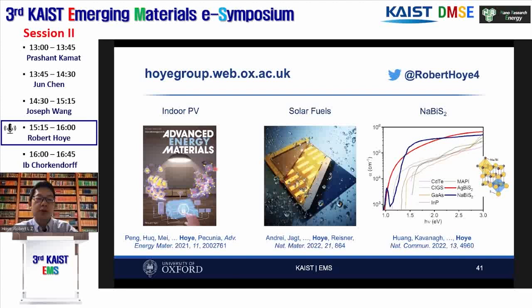So in the early part of my talk, I put forward the idea that bismuth oxyiodide, as well as many other bismuth and antimony-based perovskite and spinel materials, have a lot of potential for indoor light harvesting because wide band gaps close to 2 eV are ideal for harvesting visible light indoors. And this is important to power Internet of Things electronics. I also showed you that bismuth oxyiodide is a promising photocathode material with suitable properties for water splitting as well as for CO2 reduction. I showed you that we were able to demonstrate the first oxide-based photoelectrochemical tandem that could